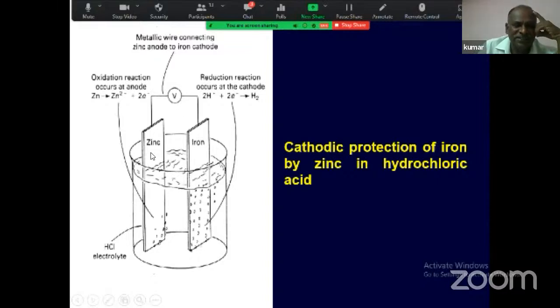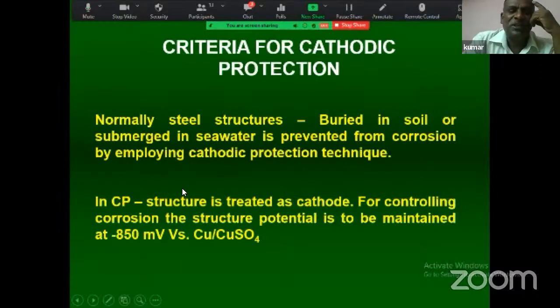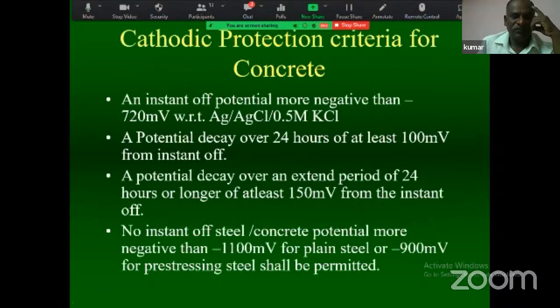You see here, this is the way. Zinc will dissolve like this, Zn2+ and 2e-. And here, at the cathode, when you are connecting, automatically the cathodic reaction happens. The iron is getting protected even in the hydrochloric acid if it is connected together. That is called a sacrificial protection system. I will go like this.